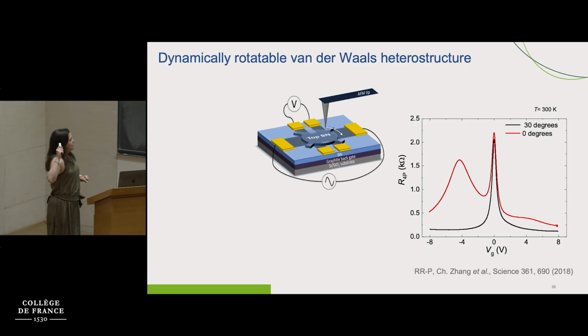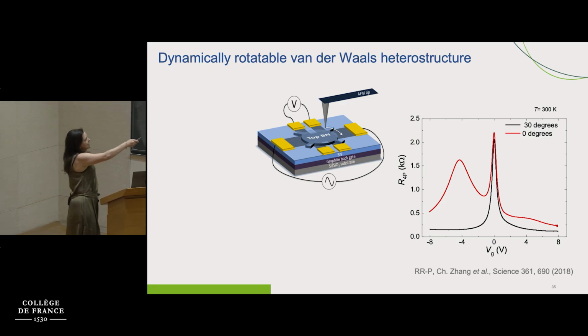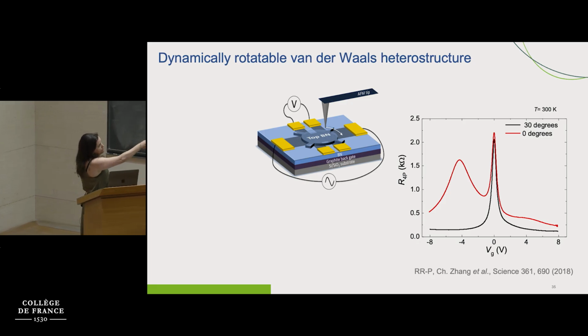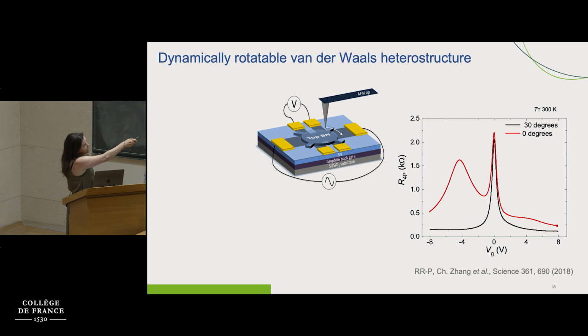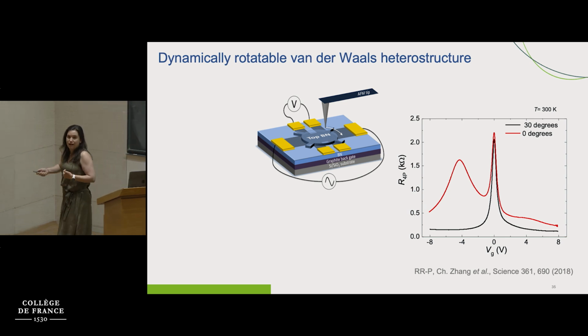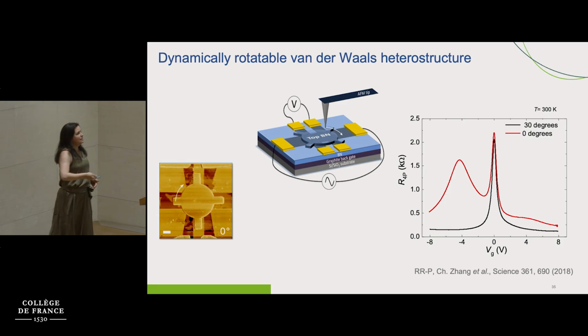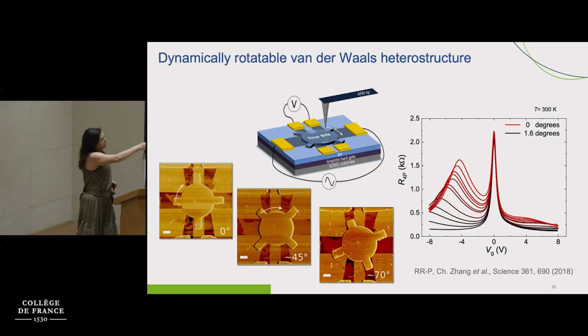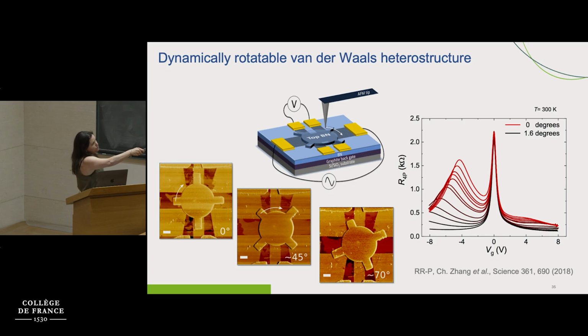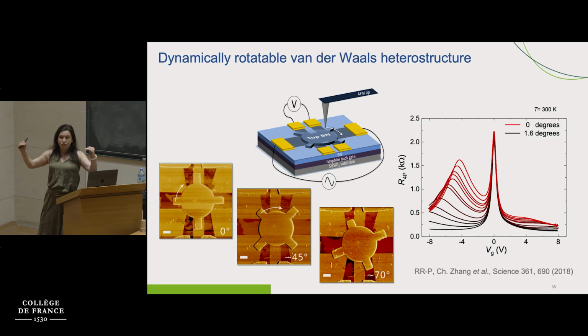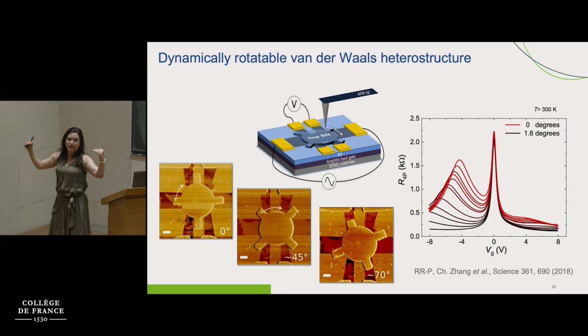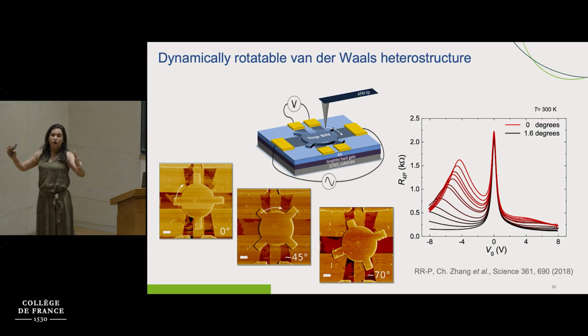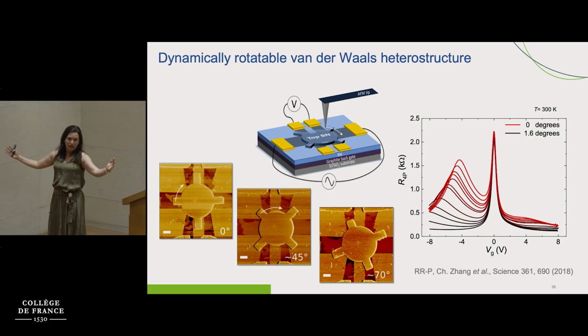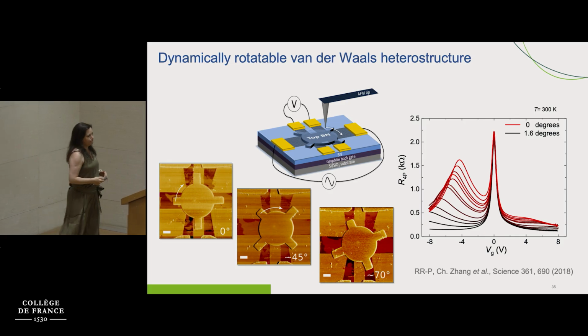So a long time ago at Columbia, we developed a technique where, using an AFM tip, we are able to continuously change the orientation between graphene and BN, and you can see that as we change this orientation continuously, this peak moves, because the position in energy of the satellite peaks is going to go down and up. This is just the band folding being larger or smaller.